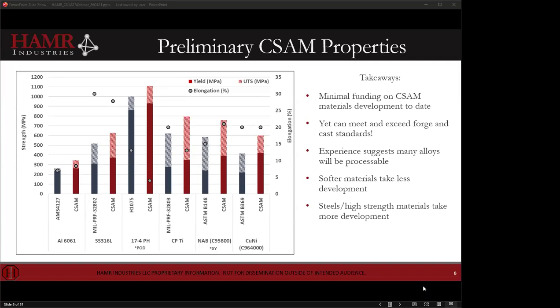And then when we look at some of the maybe higher strength, more challenging materials, we see cold spray starts to struggle a little bit. It tends to have good strength, and then we tend to have a little bit lower elongation. But again, I'll note a lot of this goes back to development. These are some of the least developed materials, and we already have good strength out of them, and it's just working on getting Z strength up. So 316, for example, is 27 versus 30% elongation. So pretty close to what we're trying to get with the MIL PRF standard in cold spray with effectively zero development.